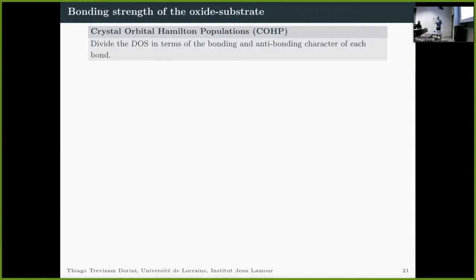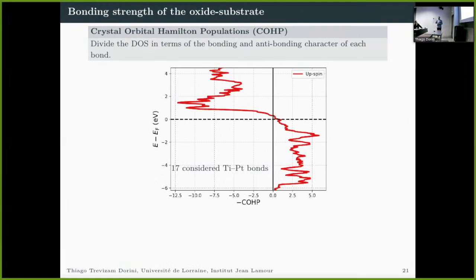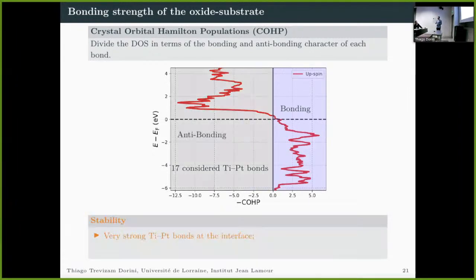And for this, we have used the crystal orbital Hamilton population. In this methodology, what we do is we divide the density of states in terms of the bonding and anti-bonding characteristics for each bond. And here, for the titanium-platinum bond, we have made the average of 17 bonds in this system. And here we have the results for this analysis. So how can we read this graph? In blue, we have the bonding states for these bonds. And in gray, we have the anti-bonding states. And as you can see, for all energy levels on the occupied states, we have only a bonding characteristic for this bond, and we have the anti-bonding character only for the non-occupied states. Which leads us to conclude that there's a very strong titanium-platinum bond at the interface.